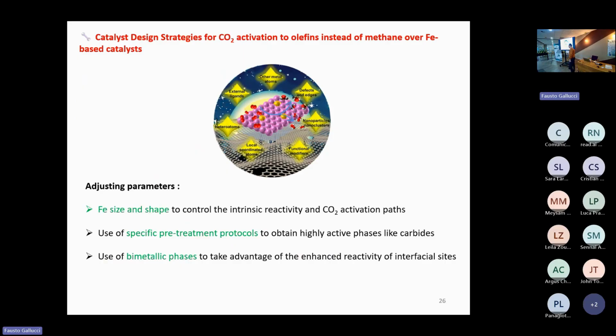Let's now see the corresponding strategies in the case of CO2 activation to olefins, the most demanding process, instead of methane. In this case, the adjustment parameters involve the iron size and shape, the use of specific pretreatment protocols in order to obtain highly active carbide phases, and the use of bimetallic phases to take advantage of the synergistic interactions between iron and other transition metals, as I will show you later.